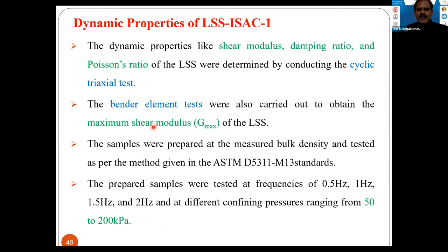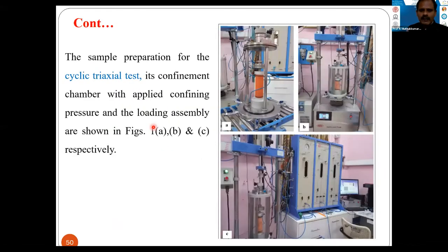So we have considered various frequencies from low to high, 0.5 to 2 Hertz, with various confining pressures, 50 to 200 kilopascal. So considering from the top surface to 3 to 5 meter depth, which is our point of interest with respect to the foundation. So that is what we did.